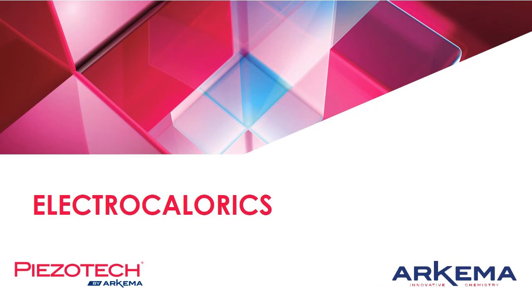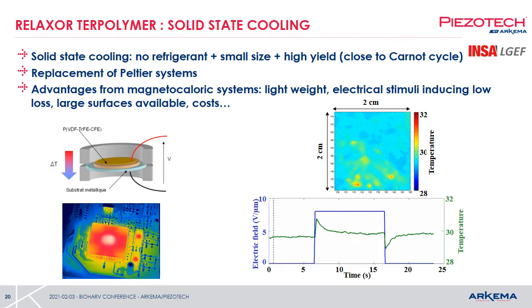One last application, and also let's say more long-term, but kind of an amazing one, is the electrocaloric application. So the electrocaloric, what is it? It is that when you apply an electric field onto the terpolymer, so not the copolymer, but relaxor terpolymer, especially CFE ones, you're going to orientate the dipoles. So when you orient the dipoles, what is going on? It is highlighted in a small video on the bottom. So at zero electric field, the terpolymer layer is at room temperature. When you apply an electric field, you're going to align the dipoles. So when you align the dipoles, you're going to decrease the entropy. So you're going to release heat. So the terpolymer layer will heat up. Then the heat will be released into the air.